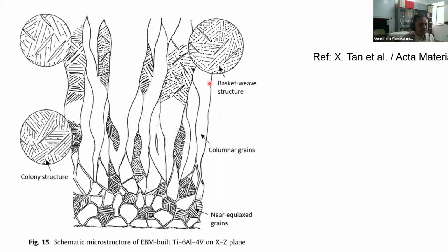Similarly, if you take a component that is not subjected to a directional load, equiaxed grains are perhaps preferred because they have a lot of grain boundary area which can absorb the energy in propagation of any crack, and therefore they are fairly tough. And so one may prefer equiaxed microstructure in certain applications. And there are also applications where we want to very carefully ensure that the basket weave microstructure is aligned in such a way that it gives you good toughness.